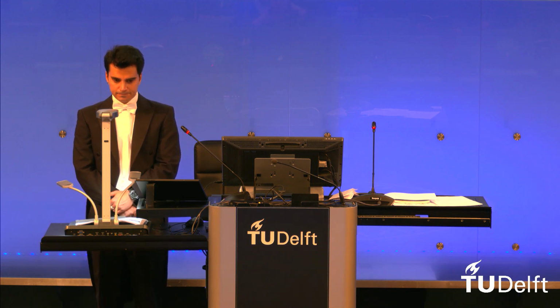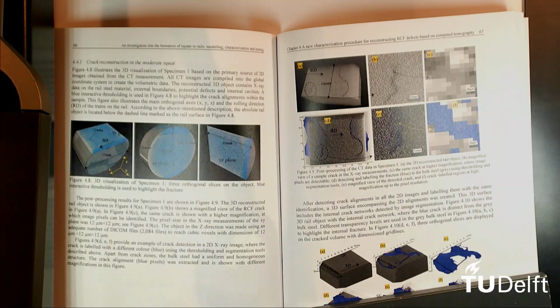The most important point I would like to ask, let's go to that then. You detect a difference in density, and that means that the crack should be more or less open, right? If a crack is closed, you don't have a difference in density. So the crack should be a gap, actually. And how big must that gap be in order to call it a crack? Is that the detectability of 200 nanometers that you mentioned?